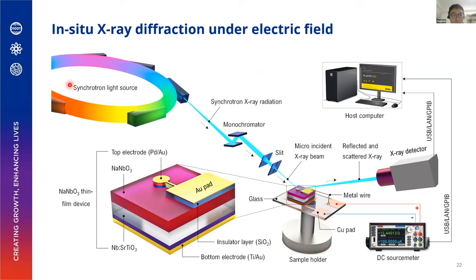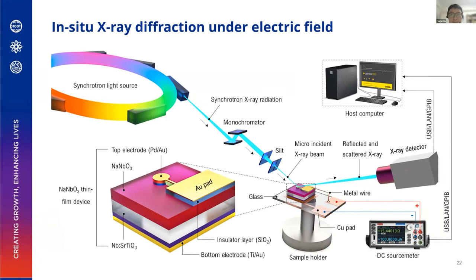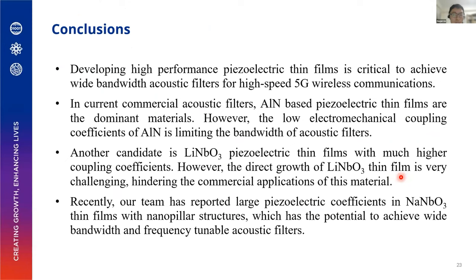So one of my staff put up this schematic to try, using a micro size or even nanometer size beam, to look at our device and to see electric field induced phase transitions or structure change under the electric field. And another thing is that because our device is going to work at around the gigahertz frequency range, I think there's also the possibility to use time resolved X-ray diffraction to look at some of the dynamics in these resonator devices. Okay, I think that's my conclusion.